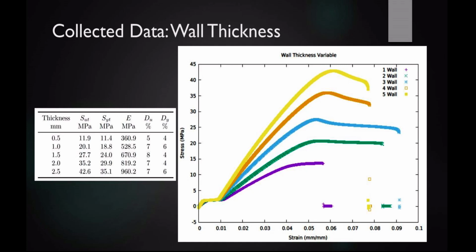Then we see the actual curves themselves look fairly nice. One wall here and two wall don't really curve down the same way as 3 wall, 4 wall, and 5 wall do, which points to a stress concentration being added in the later ranges of that ductility. You're seeing the effect of the infill pushing against the wall and then causing a stress concentration to form and early failure. With 3, 4, and 5, the wall is just thick enough where it can basically push back against that stress concentration, and it'll neck nicely and then fail like you would expect from a metal specimen.